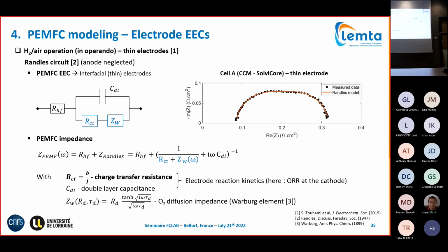So here again, what you see is your Randles circuit. What we call the Randles circuit is the parallel connection between the double layer capacitance, the charge transfer resistance, and the Warburg element, the diffusion impedance. That's the cathode. This is in series with what we call the high frequency resistance. The high frequency resistance is actually majorly dominated by ion conduction in the membrane, plus the different interface resistances between different materials. The charge transfer resistance is linked to the reaction kinetics and can be expressed through the Tafel slope, law, and the cell current.